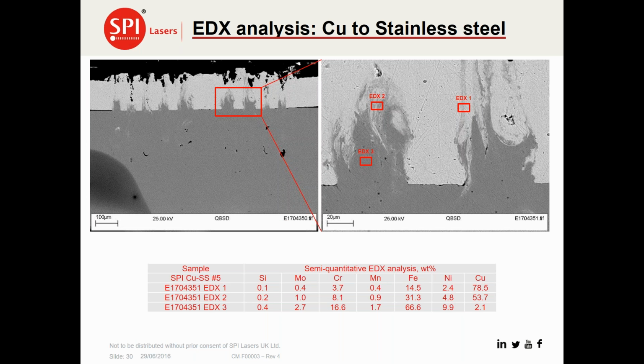Here's another example of an EDX for copper to stainless steel. Again, you can see on the image, particularly on the right, the copper on top onto the stainless on bottom, there is a distinctive mix of the metals, but again, no change in the metallurgy itself. You still just have copper there and stainless, but they exist in different layers. You can see here that as it's mixing, it's creating this mechanical bond. Some people have referred to this as almost like raspberry ripple ice cream, where you are mixing the two liquid metals at the time, and then solidifying, but not actually mixing it at a molecular level.